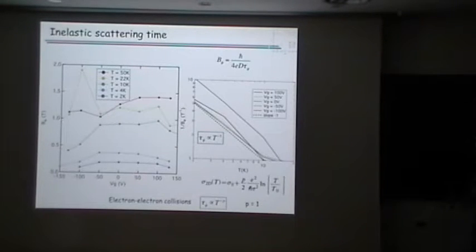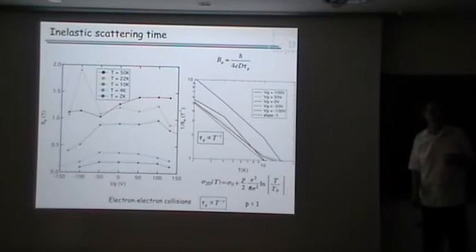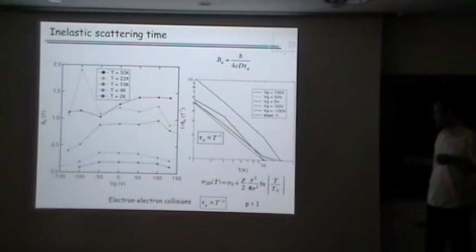Now, what about the inelastic scattering time? Okay, we have better data. This is like 5 months ago data. But basically, what you see is that it's roughly constant with the gate voltage. Roughly, I mean, there is more variation. But more important, of course, the scattering time is decreasing with temperature as we expect. And if you plot the scattering time as a function of temperature, roughly, on a log scale, it's a linear slope. This is exactly what you expect if electron-electron scattering interactions are the most important scattering processes.